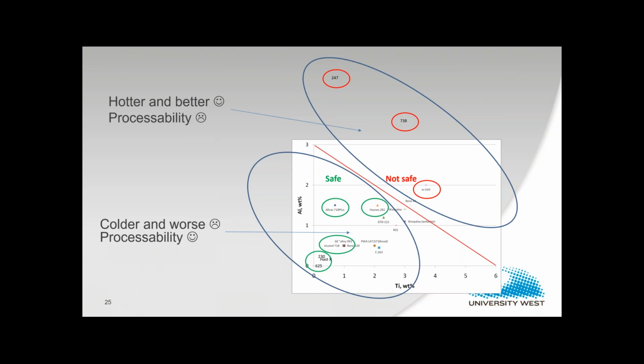So if we consider superalloys, and specifically the precipitation hardening nickel-based superalloys, one driver or ambition is to use materials that can sustain a higher service temperature compared to, let's say, the standard workhorse 718. So one way to accomplish that is to add more aluminium and titanium to the chemical stew. So aluminium and titanium push up the amount of hardening phase, specifically the gamma prime strengthening phase. The problem is that if you push the gamma prime content through the roof, you get a very bad processability, or a very high risk of cracking, not least strain-age cracking. So it's always a balance between service performance and processability when you develop a new alloy.